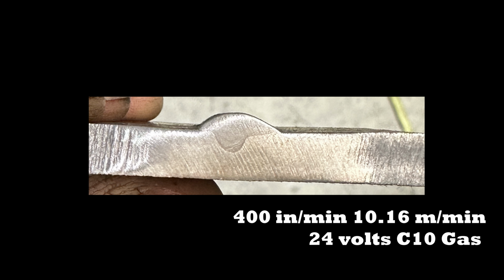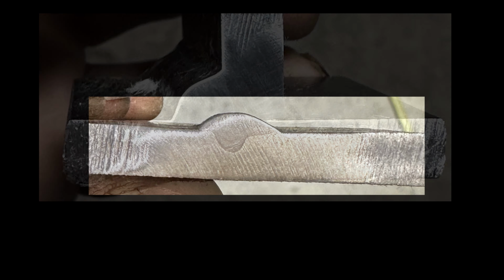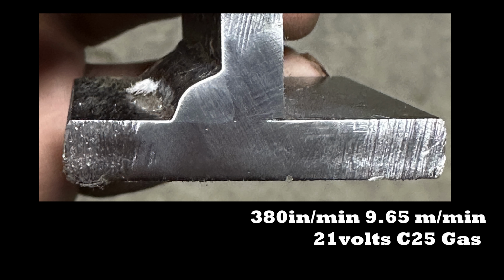When you do fillet welds with it, you're going to see that it punches way in and deep, and it produces an overall flat weld versus the more or less convex weld you're going to see with the short circuit process. Now let's look at some fillet welds. This is the best that you're really going to get at about 200 amps with the short circuit process. It's really not going to get any better. There is some root fusion. There is a little bit of penetration here. This was done pulling because pulling increases penetration with the short circuit process. You can see the bead is not really roped up, but it's far from flat. This is overall an acceptable, decent short circuit weld, and this is what you should be striving for.